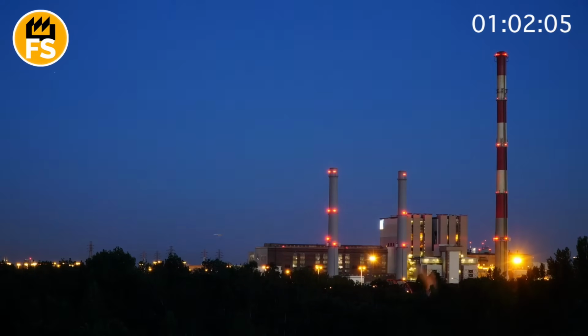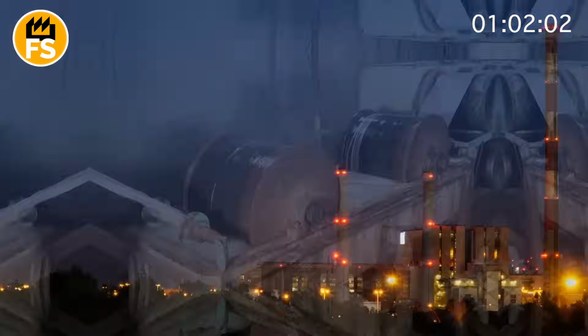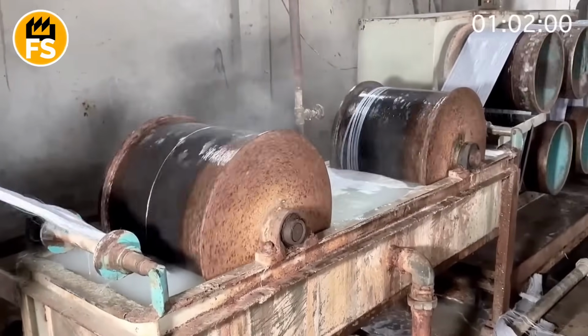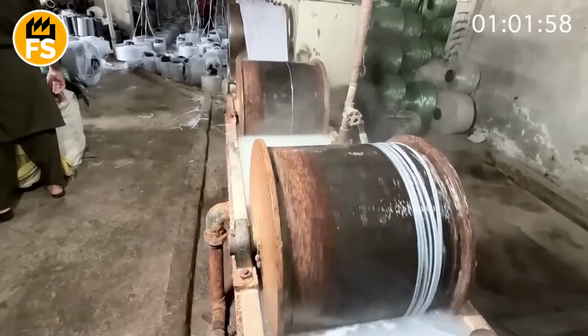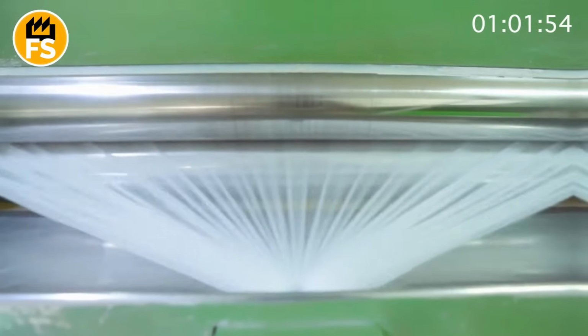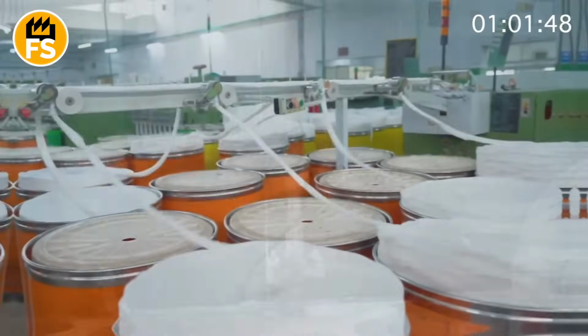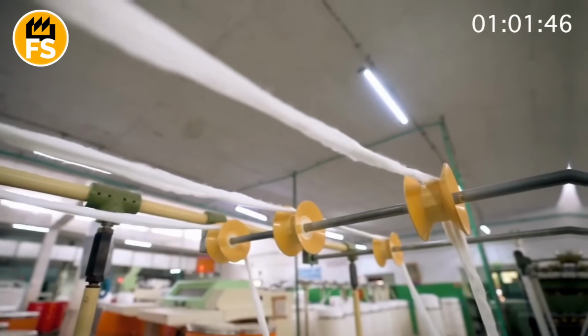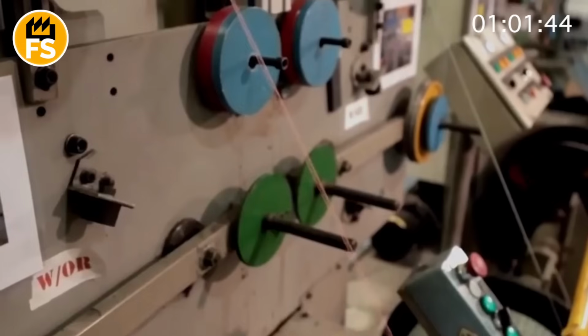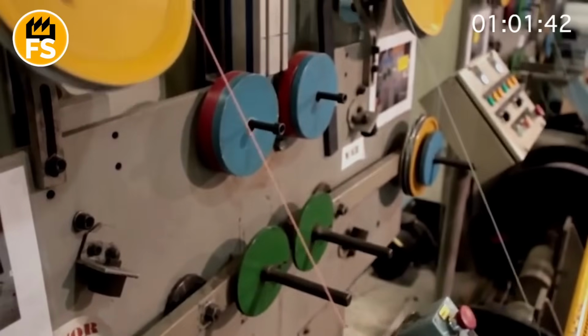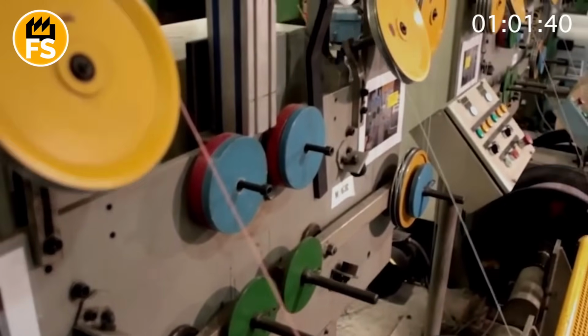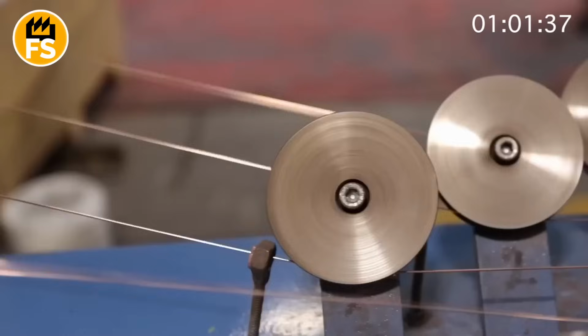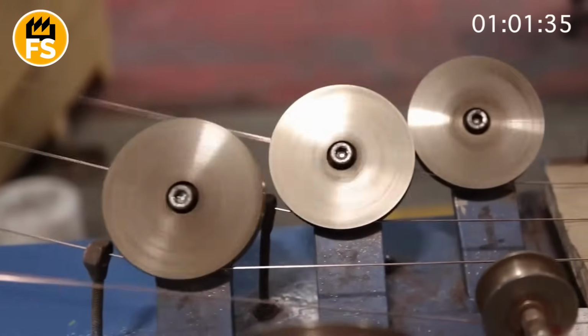Each pass through the die reduces the wire's diameter by a few percent. It's like passing through increasingly tight doors, forcing the material to stretch. After a dozen such passes, a thick rod half an inch in diameter becomes a slender strand 0.1 inch thick or even less. During drawing, the wire heats up from friction, so it's constantly cooled with water or special lubricants. Without this, it would overheat, lose its shape, or even break.